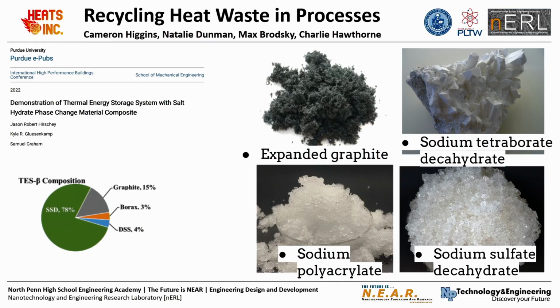Some of the substances here may seem alien to you, but the first one is expanded graphite. That is a heat-treated and acid-treated version of graphite. On the right is borax, which is the nucleating agent. It makes sure that the phase change material, which is the sodium sulfate decahydrate, stays in optimal temperatures for freezing and melting. And then the sodium polyacrylate is an absorbent used in diapers. That is so we can absorb the phase change material once it melts.